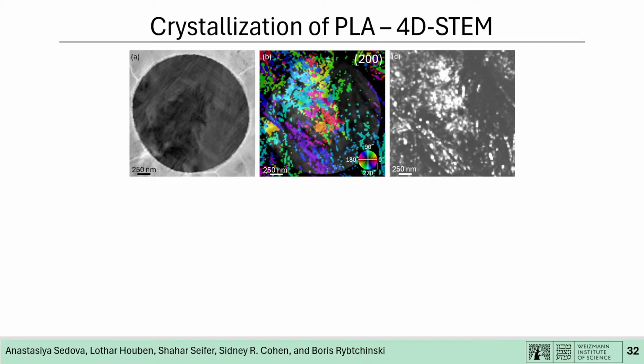We can obtain fluctuation maps. Fluctuation maps are the variance of intensity normalized by mean intensity. In the case of polymers, it's important because polymers are semi-crystalline materials. They have amorphous regions and crystalline regions. Here we can see that it's very sensitive to crystallization. The dark parts are the amorphous parts and the shiny parts are basically the crystalline regions. We can isolate lamellae.